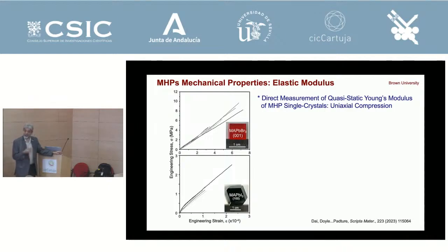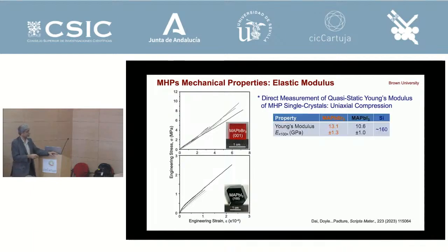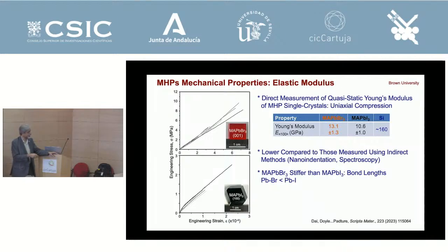And so we made single crystals. You can actually make single crystals very easily in the sense that at room temperature, but with some expertise. You just leave it in the beaker for a week, and you make beautiful centimeter-sized crystals. And so we did direct measurement using stress strain in compression, and measured the Young's modulus. For example, this is MAPbBr3, and this is MAPbI3. This is about 13 GPa, and this about 11 GPa, compared to silicon, which is about 160 GPa. And by the way, the reason why this is stiffer is because it is basically controlled by the lead-bromine bond. And that bond distance is smaller in the case of bromine compared to iodine. That's why this material is stiffer. That's the work of my former PhD student.